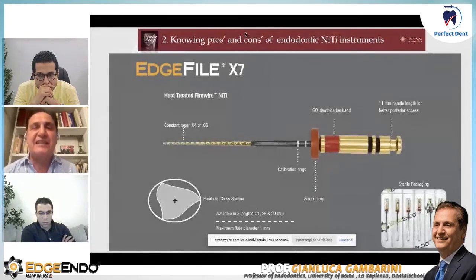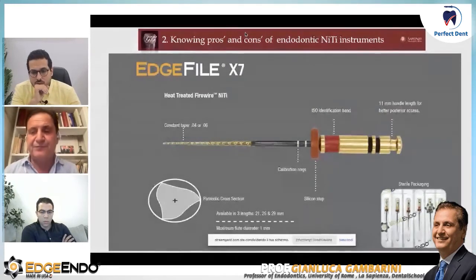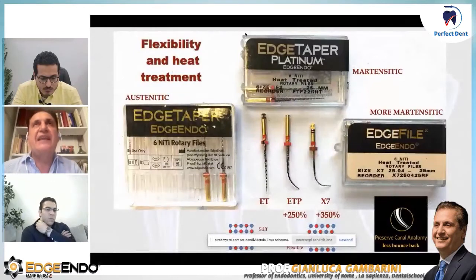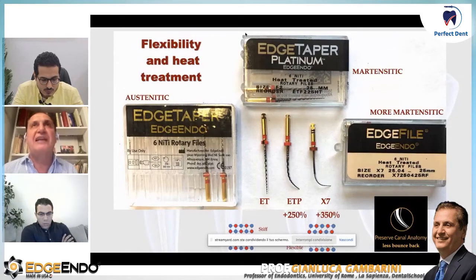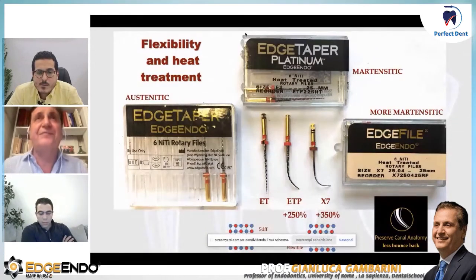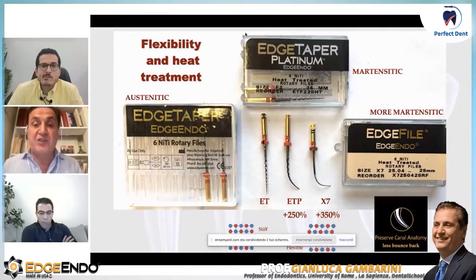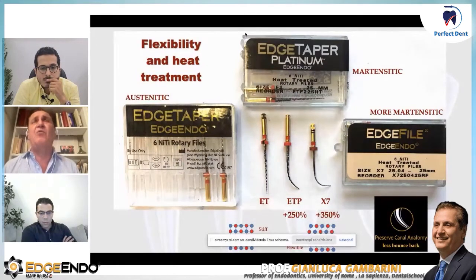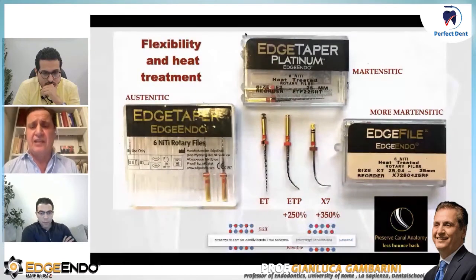But what is very important is that this is a very, very peculiar file, which is, in my opinion, great for complex curvature. The reason why I'm saying this is that I showed you before the EdgeTaper traditional NiTi and the EdgeTaper Platinum heat-treated NiTi file. So we had an increase of 2.5 times. And with the X7, because of the design, because of the dimensions, here we have the same size 25 file, we have a much better increase of the properties. And the other interesting thing about flexibility is that one is flexibility, the other one is elastic return. So with this martensitic file, we have less bounce back. What does it mean?